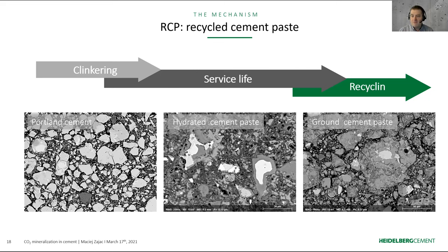One of the key parameters, however, is the content of the paste in the recycled concrete paste, the cement paste. This needs to be as high as possible, since obviously the aggregates, independent of what kind, are not reactive with respect to carbonation and hydration. In other words, they neither sequester CO2 nor bring compressive strength later on. So in order to maximize the content of the aluminosilicate gel in the paste, we need to maximize the content of the paste itself in the RCP. This is still ongoing work, and hopefully I will be able to share more information with you in the next years.